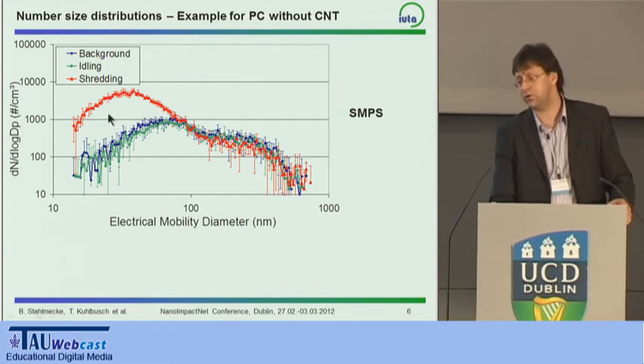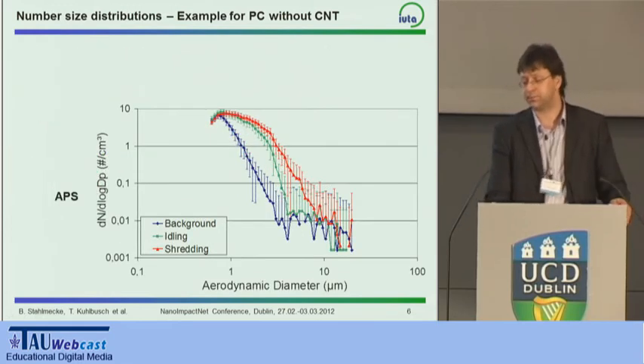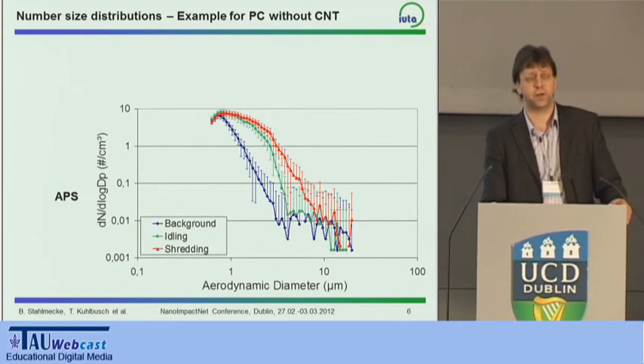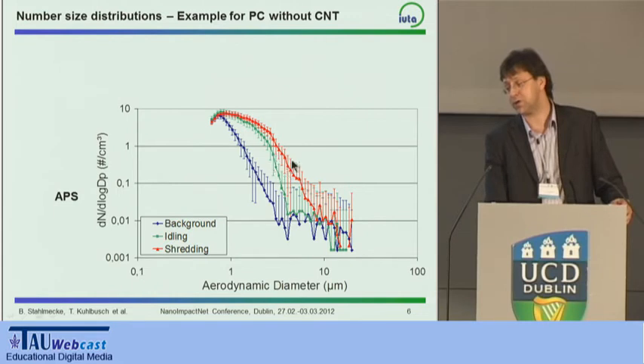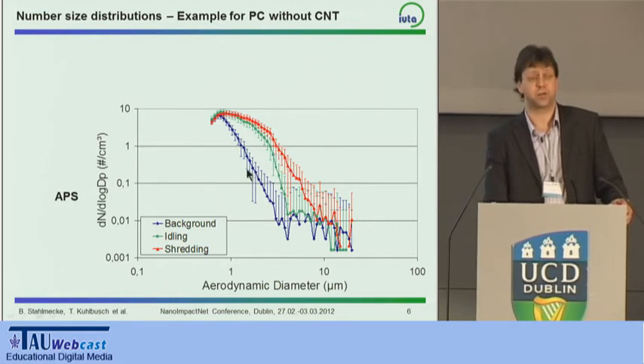And then we looked into the ratios to better show the modes of particles released by the different processes. Here is the same as shown for the SMPS, now for the APS, which covers the size range from 700 nanometers to about 20 micrometers. Similarly here, you see the background concentration, an increase as soon as idling starts, and then as the actual shredding process starts, in red, you see some release of material with the polycarbonate.